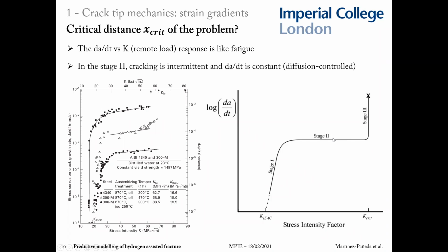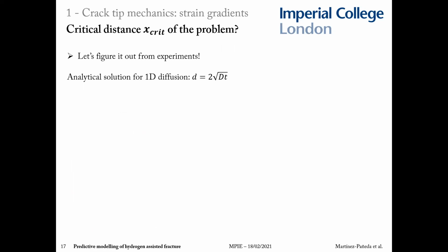And finally, the rupture. And the reason why the crack speed is constant in the stage 2 is because crack growth is diffusion limited. You have enough mechanical driving force, so to say, but you need to wait for the hydrogen atoms to reach the critical distance ahead of the crack. So cracking is intermittent here. The crack does small jumps as the hydrogen atoms reach the critical distance. And since we know how much time it takes for hydrogen to travel a certain distance, d, for a material with a diffusion coefficient capital D, then we can use experimental data to determine what this critical distance and what this critical time is.